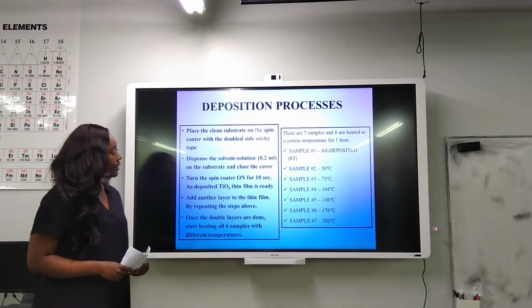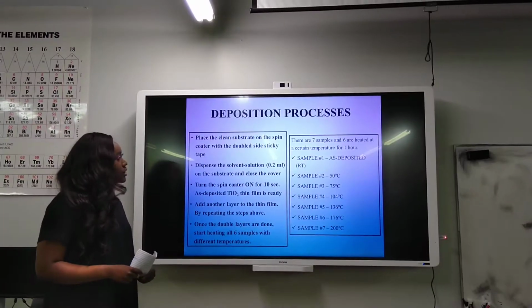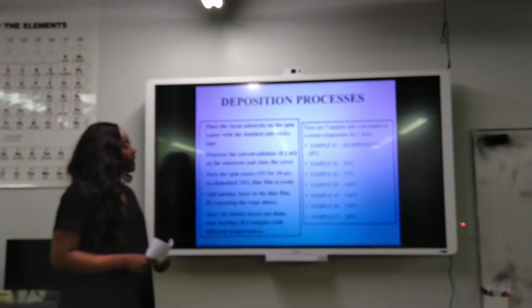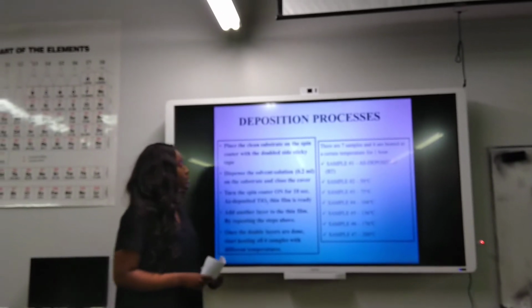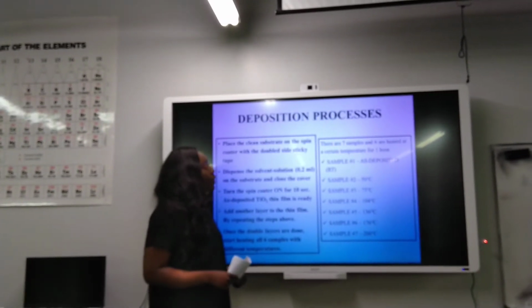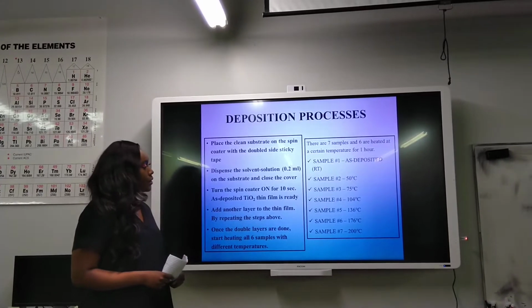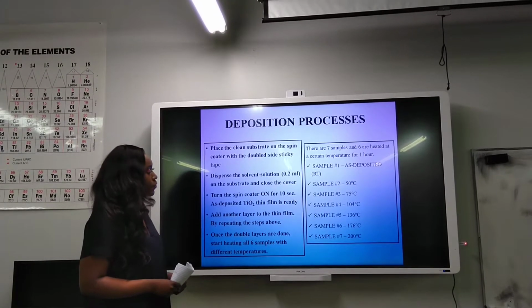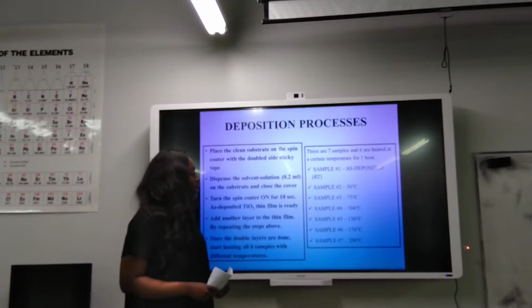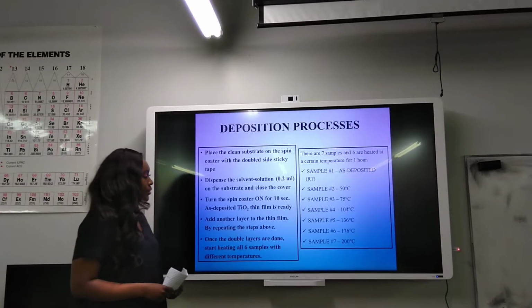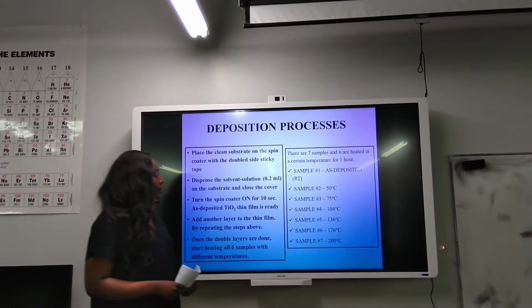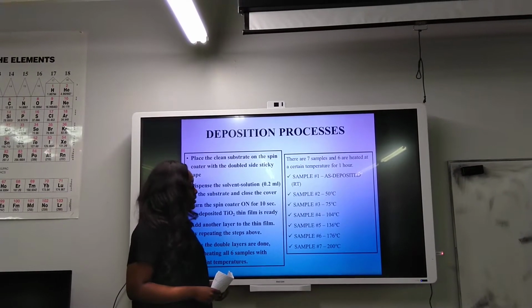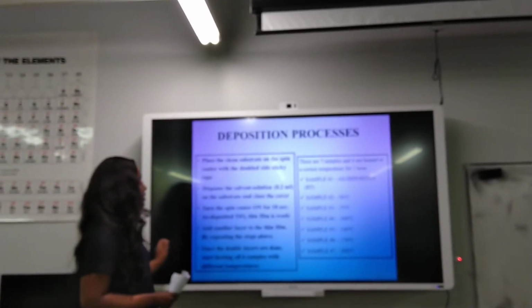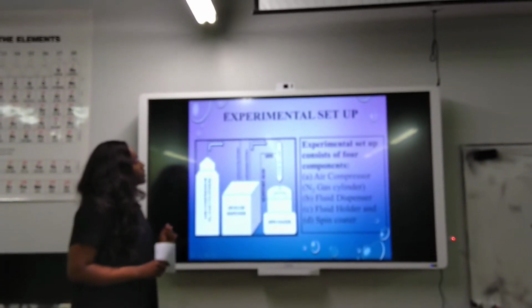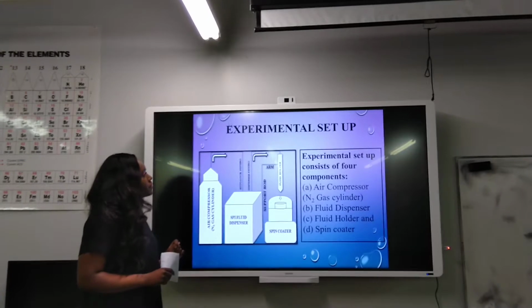So in total we did 7 samples, and they were all heated at different temperatures. Like sample 1 was as deposited, sample 2 was 50 degrees Celsius, sample 3 was 75 degrees Celsius, sample 4 was 104 degrees Celsius, sample 5 was 136 degrees Celsius, and sample 6 was 176 degrees Celsius, and sample 7 was 200 degrees Celsius. So this is the experimental setup.